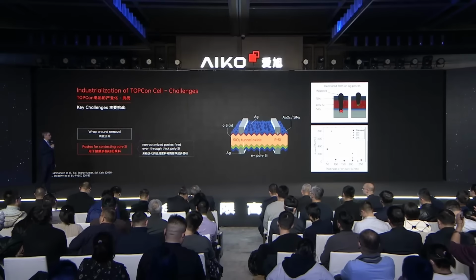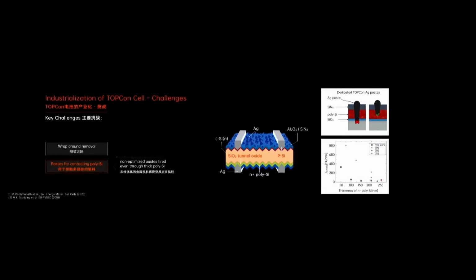Then another topic which was addressed was the development of the silver paste for contacting polysilicon layers. In the beginning, standard silver paste for contacting phosphorus-doped emitters was used, and these quite readily fired through even thick polysilicon layers. But with each generation, the paste makers improved the paste and got a better understanding of how to design the paste so that it minimally penetrates the polysilicon, and today we can contact polysilicon layers as thin as 80 or 90 nanometers without suffering from enhanced recombination losses.